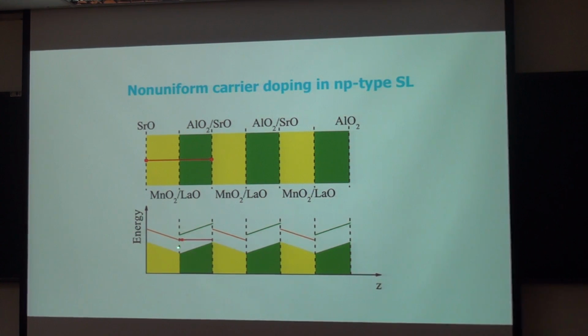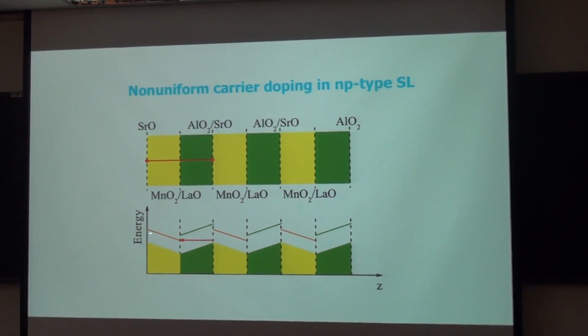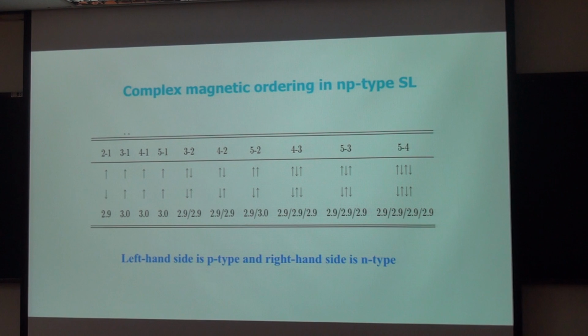But obviously the electron will localize at the n-type interface, while the hole is located at the p-type interface. So there's a non-uniform carrier distribution in the superlattice structure, and the consequence is that non-uniform magnetic ordering develops in this superlattice. For example, in this case, the right-hand side is n-type, and the left-hand side is p-type. At the n-type interface, ferromagnetic ordering is developed, but the p-type interface is still antiferromagnetic. So we use superlattice structure to realize complex magnetic ordering in this system.